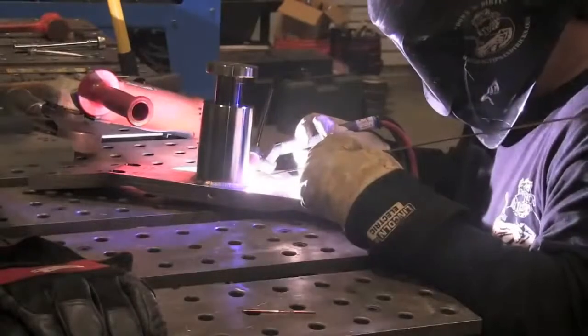Outside corner joints, amperage settings, low alloy steel TIG: 160 amps first pass, coming back over it with a second pass at slightly lower amps while maintaining an interpass temperature of 500 degrees to prevent any kind of hardening going on in the high strength low alloy steels.